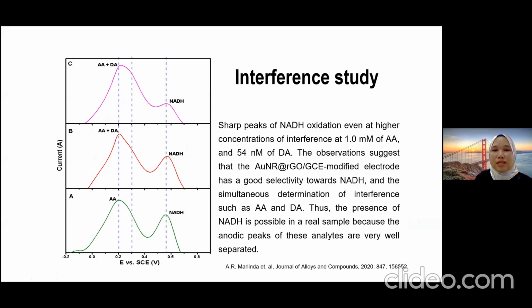We also study the interference. So we can see that introduction of NADH obviously shows the separation even at a higher concentration. So ABC shows an increment in the interference concentration of ascorbic acid and dopamine. But for NADH, as you can see from the figure here, it shows a very significant separate peak compared to the others. Okay, so it is possible for a real-time sample because of this anodic peak, and it can also be well separated even in the presence of many interferences.